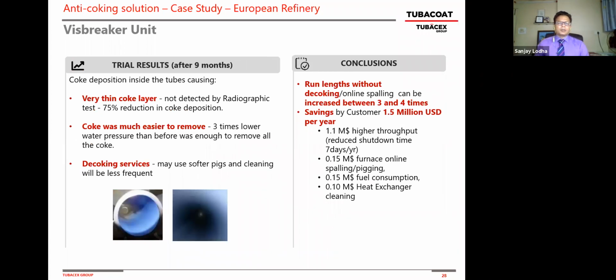So, trial after 9 months. Now it's been 14 months, but this was done at the 9 months. What we saw after 9 months is a very thin coke layer, not even detected by the radiographic test, and in essence, 75% reduction in the coke deposition. And whatever coke was there was very, very easy to remove, with 3 times lower water pressure. You can just put some water and it will come off.